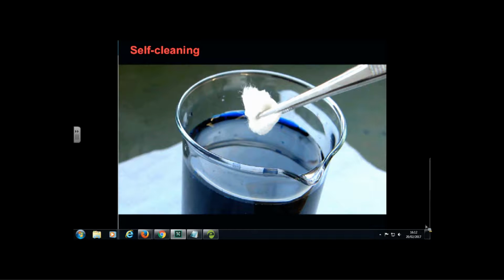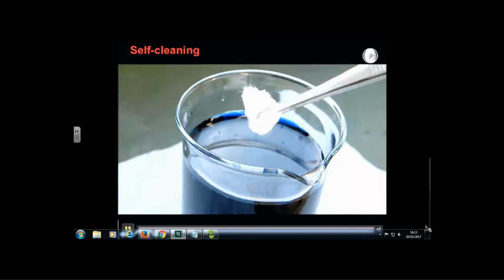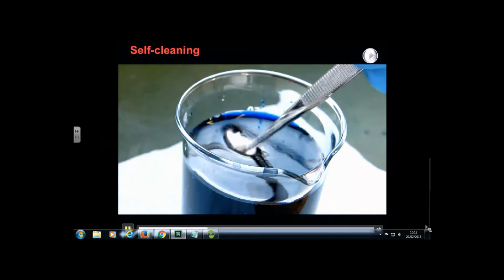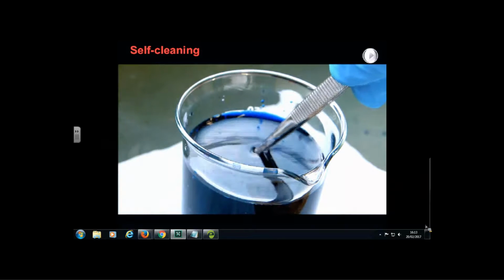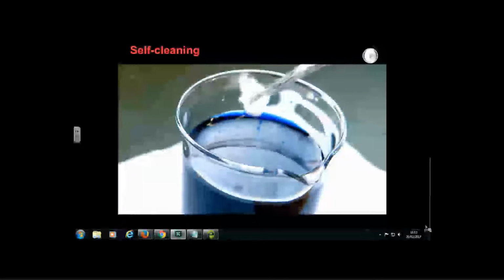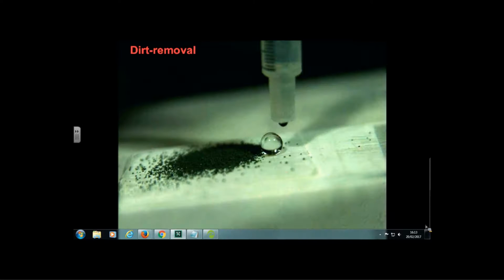So here we have a solution with methylene blue dye, a very strong staining agent, and we're going to dip into that solution the superhydrophobic cotton wool which we've made - we've taken cotton wool and treated it with our superhydrophobic material. When we put it into the dye solution and take it out, it's absolutely pristine, so it doesn't undergo any wetting at all.